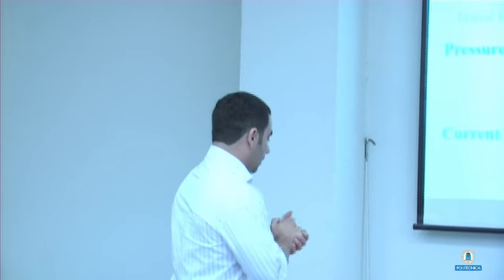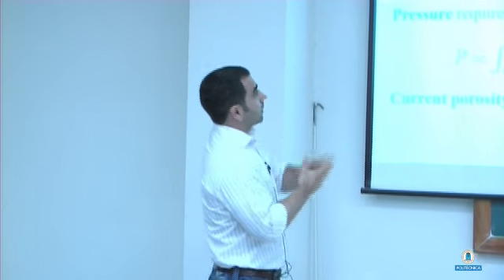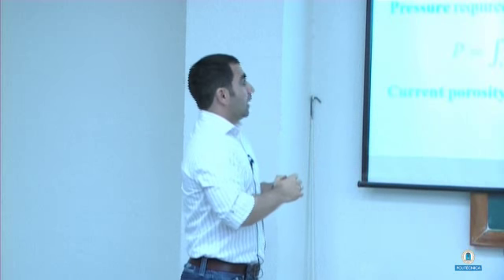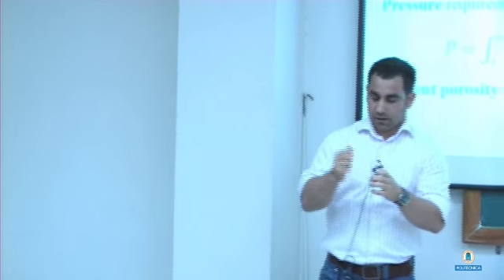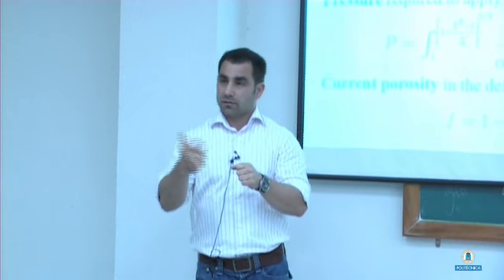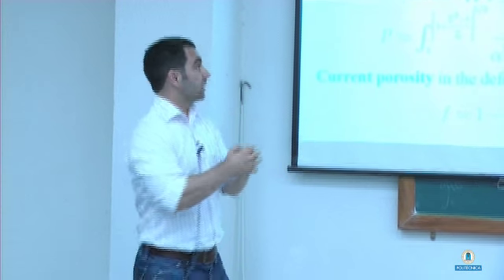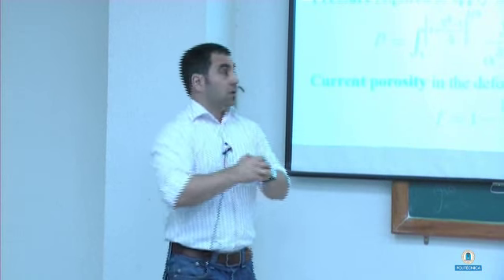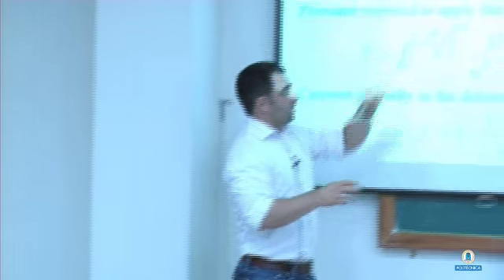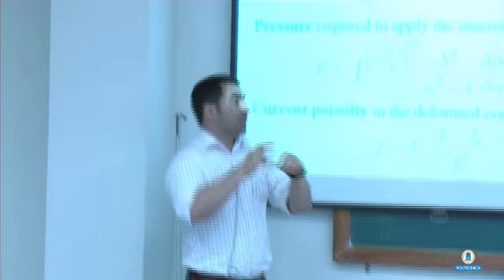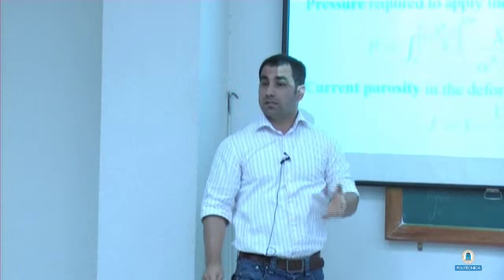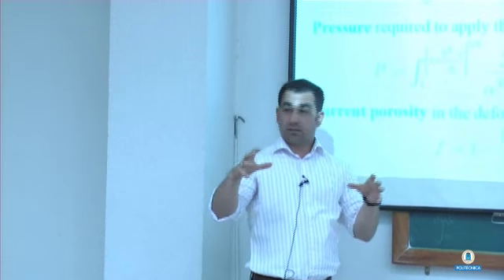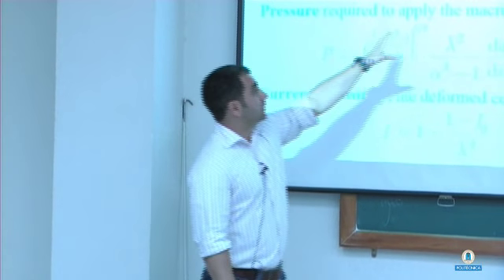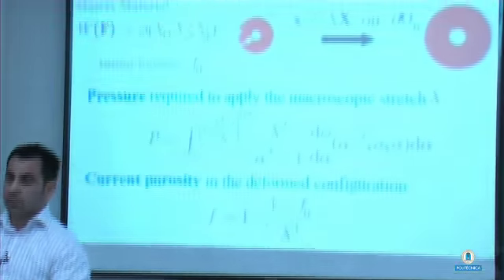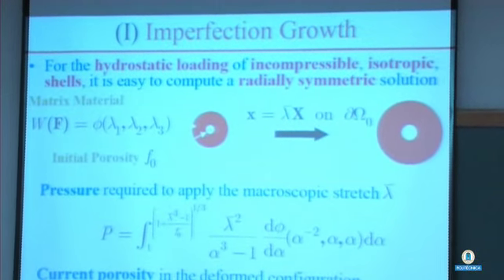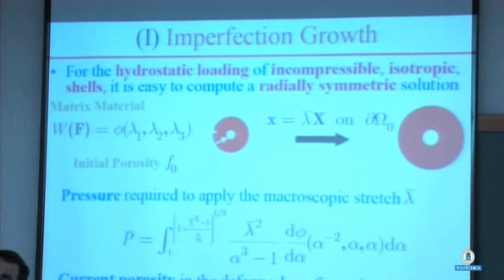Okay, so now, very quickly, let me show you what is known about cavitation and what remains to be done. Now, what is known, let me start with the view of imperfection growth. If we consider a material that is isotropic, incompressible, right? So this is the first approximation for rubber-like materials. And we look at the problem of the shell. Well, and the shell has an initial spherical hole that is of some radius that gives you an initial porosity f0. You can apply hydrostatic loading to this shell, and you can solve this problem exactly. Basically, you can relate the pressure that you need to apply on the boundary to the deformation, the radial deformation that you get in the boundary, right?